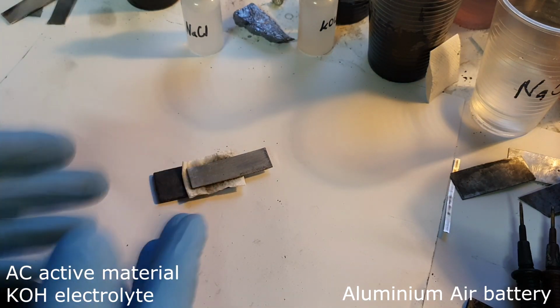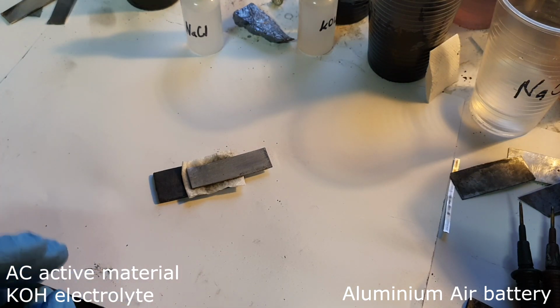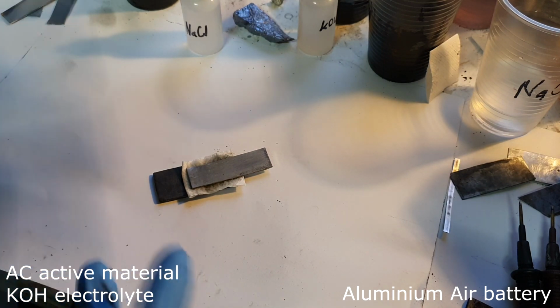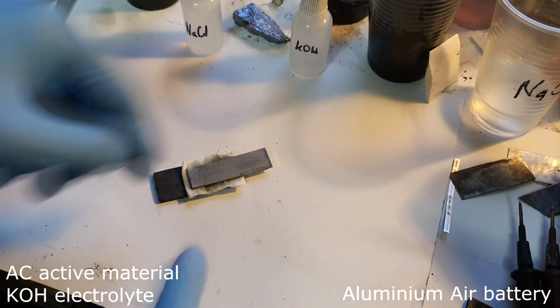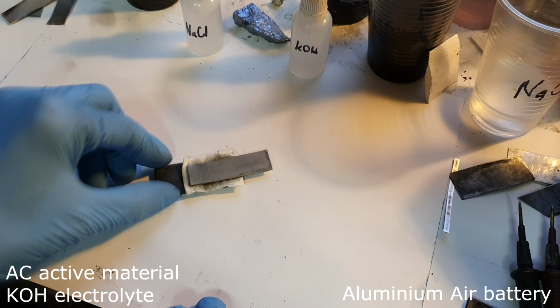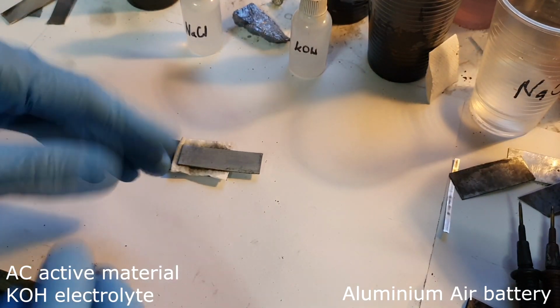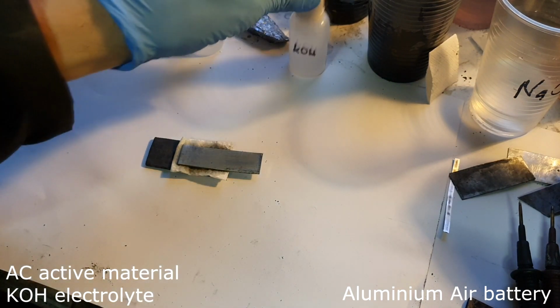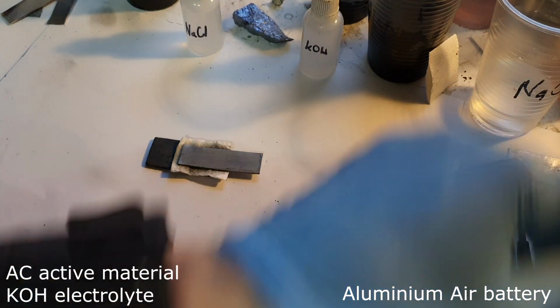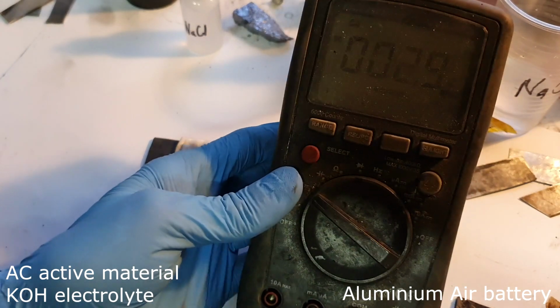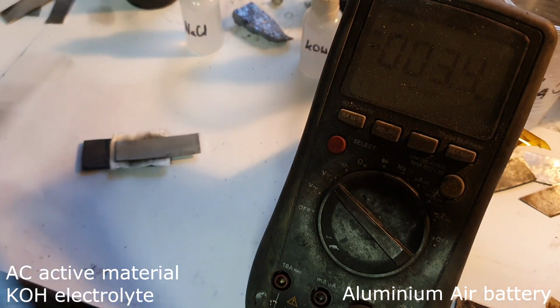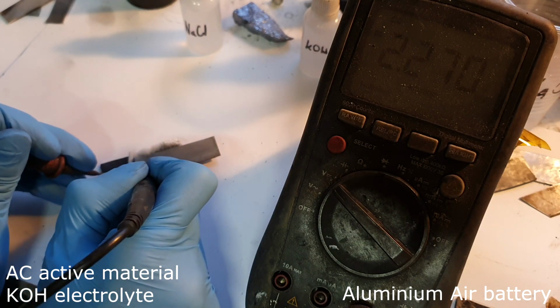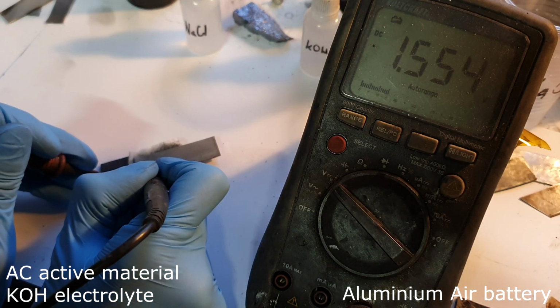So, for the positive current collector you can use a graphite plate or stainless steel. For the positive active material, you will get better performance if you use activated carbon. The separator is toilet paper, the electrolyte is 1 mole of potassium hydroxide right now, and on the top is aluminium for the negative electrode. And this is your aluminium air battery, which is really, really easy to make. But like I said, instead of potassium hydroxide, you can also use sodium hydroxide. And let's check the voltage. And with this one, I get 1.5 volts.